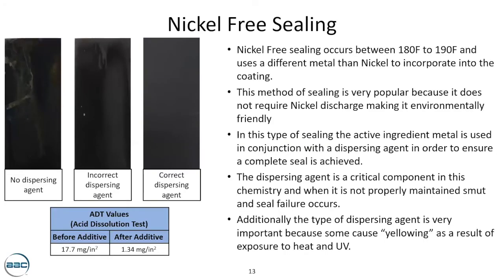All right, nickel-free sealing. Nickel-free sealing has become popular for the simple fact that managing nickel and disposing of nickel has become very challenging from an environmental perspective. The biggest challenge with nickel-free sealing is finding a nickel-free seal with the correct dispersing agent or surfactant that will also yield a good ADT and good seal quality.